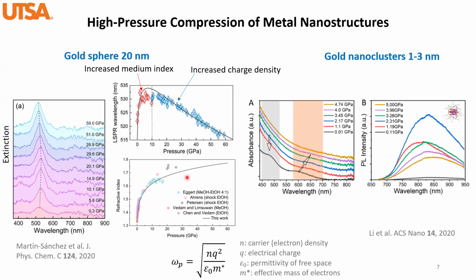And we can see from here, in terms of increased charge density, how it affects the energy, frequency and wavelength of the plasmon resonance. Here omega p is the bulk plasmon frequency, and n is the carrier density. So if the carrier density increases, you expect an increased frequency and therefore a blue shift in the spectrum.